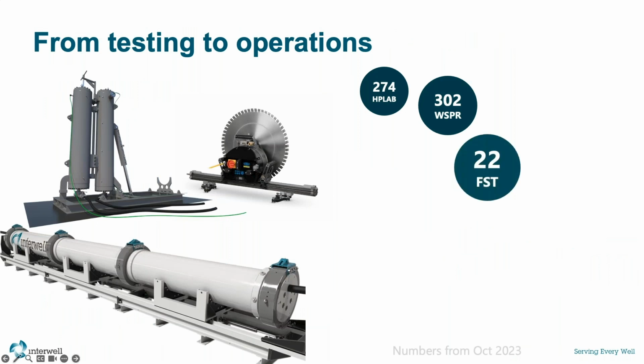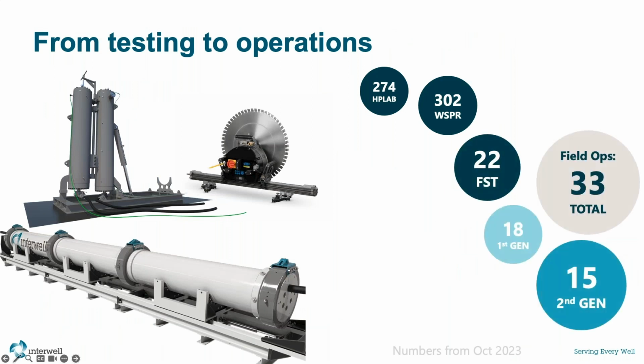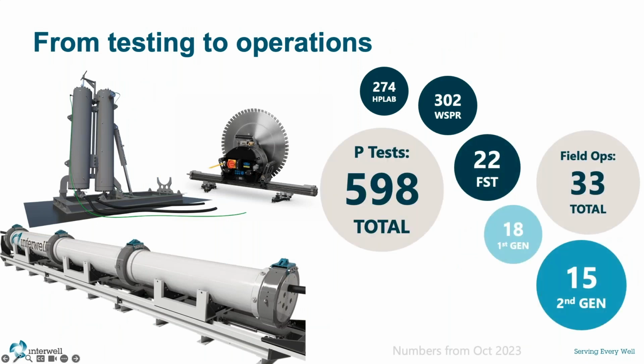So taking all of our operations from testing into the field, how can we evaluate the results of our reaction at 3,500 degrees in a downhole environment? Well, we've got some pretty specialized equipment as a result. In Norway, where our R&D lab is located, we have 4 custom-made pressure tanks designed for testing under pressure to simulate wellbore conditions. Every test that we do in half scale or full scale, we manufacture a mock-up of the well elements,